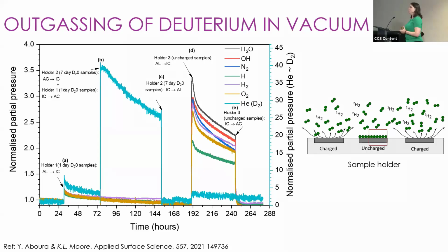In reality, what we think is this turned out to be quite advantageous for us, because if we charge a sample with deuterium, you're going to uniformly charge the whole metal surface. So if we had a cryo stage and we started imaging a uniformly deuterated sample, probably all we would detect was deuterium everywhere evenly. But by the fact that the freer deuterium that's not trapped has disappeared off into the vacuum, what we've been left with is an image which shows where the deuterium is trapped more strongly. So we're actually improving our contrast and highlighting the deuterium trap sites, which is what we wanted to investigate anyway.